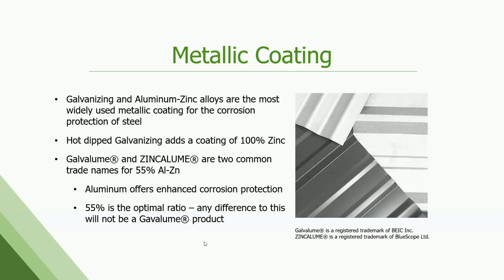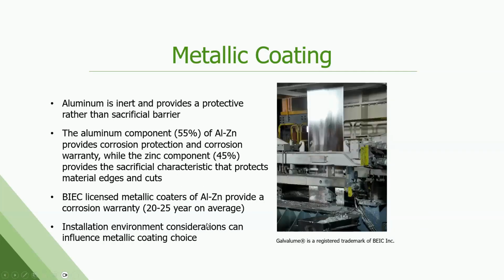The Galvalume product does come with a corrosion warranty. That aluminum component gives it much better corrosion protection long term. So you can get a corrosion warranty on that product for most applications, not all. This is also done on a very large, much larger than our paint lines, continuous line. We call them metallic coating lines. So the bare steel goes in, it gets annealed to the grade of steel it needs to be, the physical properties that steel needs to have for its end use. And then we apply either 100% zinc coating or this aluminum zinc combination.